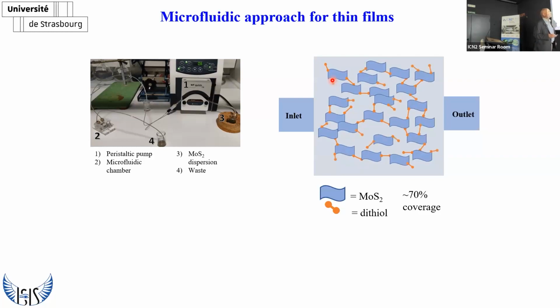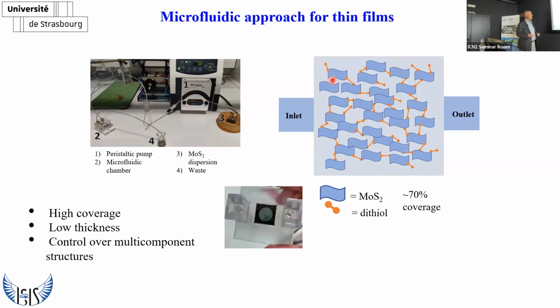We continue until the gap between the two electrodes that are on the two sides is bridged, and after each step, we measure the current passing through this kind of device until a percolation pathway is generated, and there we stop. We can start using the device for chemical sensing. Okay, and so this approach allows us to have high coverage, a very low thickness, and pretty good control over the structure of this kind of device. So the microfluidic chamber is a very banal one that we fabricated with a 3D printer in our lab.